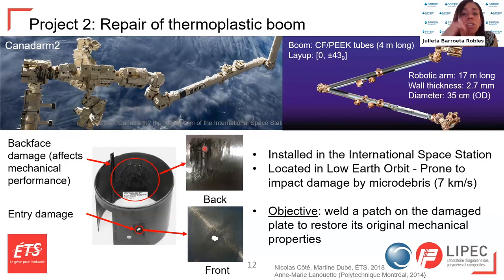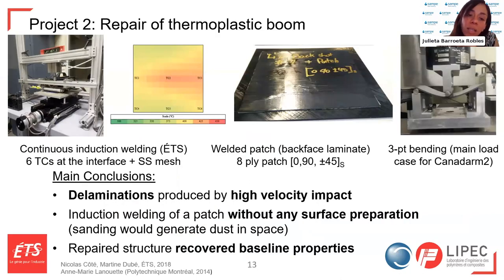So using induction welding, the goal was to explore how these components can be repaired. Similar to the previous project, there was a baseline, a damaged specimen, and a repair specimen. They were repaired using a stainless steel mesh as a susceptor in a continuous mode with the same induction welding setup. And the specimens were tested under three-point bending, which is the main load case for the Canadarm2. And the main conclusion was that they were able to produce the delamination seen in the boom by high velocity impact.